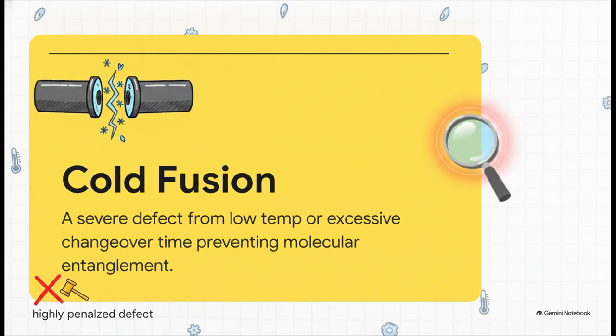Well, you induce what is known as cold fusion. This is a severe, heavily penalized defect, both on your exam and out in the field. Cold fusion is a catastrophic failure mode where the pipe surfaces simply press together without actually fusing the molecules. The polymer chains at the interface have just cooled way too much to entangle. So it creates a joint that might look totally fine visually, but possesses almost zero structural integrity.